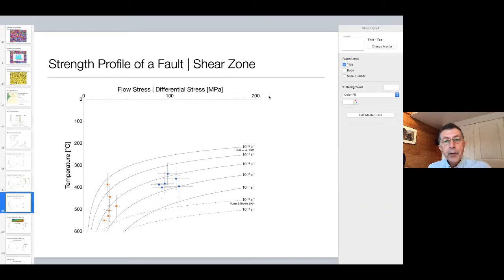So we have, again, the flow stresses and the temperatures that increase down. And these are the calculated flow stresses for the larger grains, for the high temperature grains, and these are the flow stresses for the smaller grains. We can then fit the theoretical curves of strain rates according to the equation by Hirth et al. that I've shown you before. And we see that there is a range of strain rates between 10 to the minus 12 and even 10 to the minus 15. But the majority is in this typical range of strain rates between minus 12 and minus 13, which is typical for shear zones.